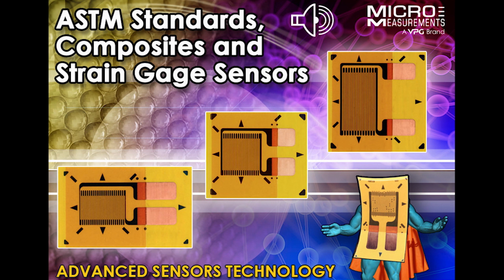And what you get out of D5379 and D7078, as we talked about in your previous podcast, is that we have actual notches to force the shear pattern to happen between the notches. There are two different types of tests in a way. D5379 is a cantilever type pushing down the specimen, while the 7078 is a bigger specimen. It looks like a bow tie with a bigger gauge in the middle, and you're trying to shear it in tension. So you're pulling and trying to rip in the other direction versus being cantilever on one side.